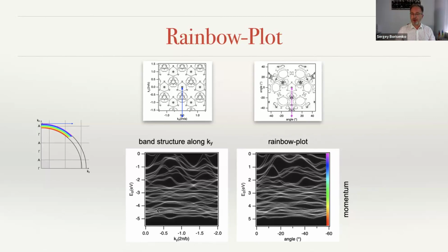So this is a typical band structure, just from the band structure calculations along the high symmetry direction, binding energy versus Ky. And this is the reconstructed rainbow plot from the band structure calculations. This is what we're supposed to see in ARPES if I say, okay, here's the band structure along this high symmetry direction. As you see, there are hardly any similarities between these two data sets, except perhaps here near zero, at very low energies, at very low angles, at very low momentum, there is a certain correspondence. You can look at the map, there is a certain correspondence when you stay close to the gamma.